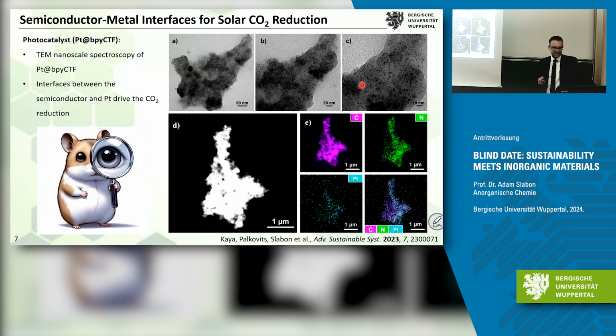So these black dots here, these are small, tiny platinum particles. And if you have this interface, you can run an integrated photocatalytic system to reduce CO2 directly to formic acid, for example.